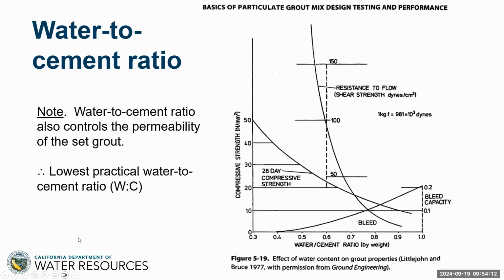And also the water cement ratio controls permeability of the set grout, which is important. But typically the permeability of cement grouts is so low anyway that a change in the region between, say, 0.4 and 1 isn't going to be critical to us. So for once, this is a secondary consideration as opposed to the stability and the strength. I hope that's a good summary. Obviously, you probably want to have a look at this graph in your own time and just think about it.